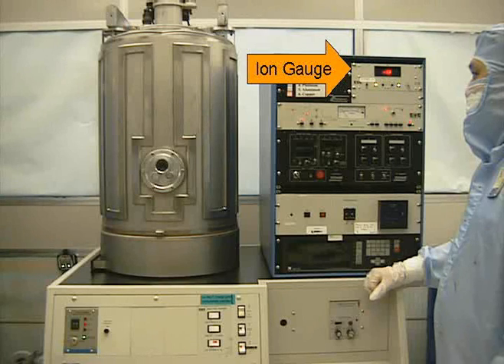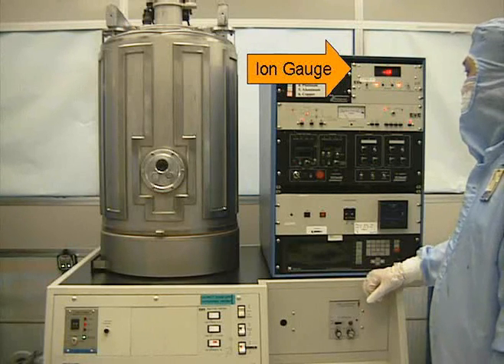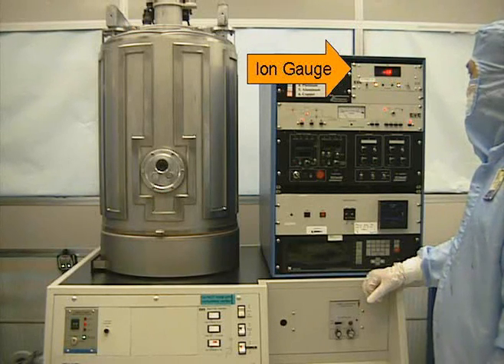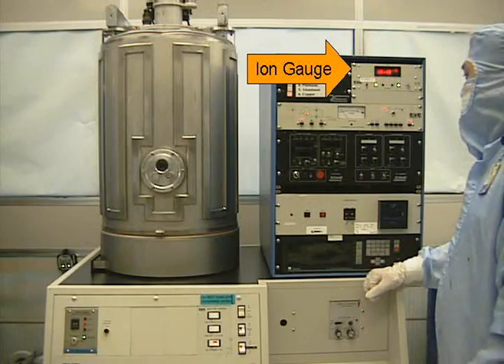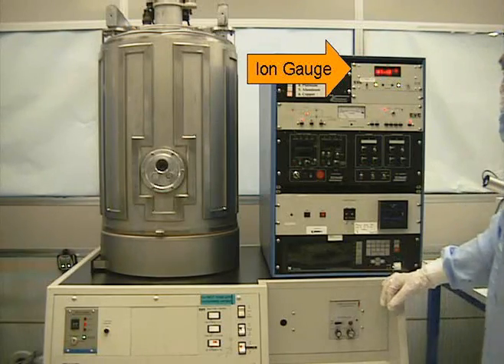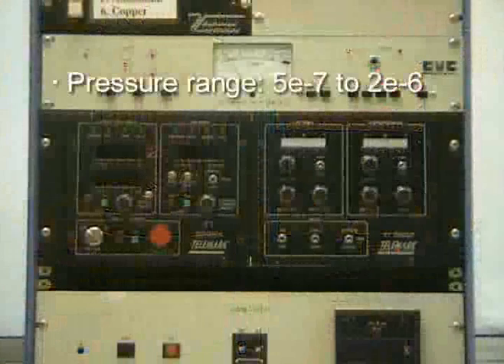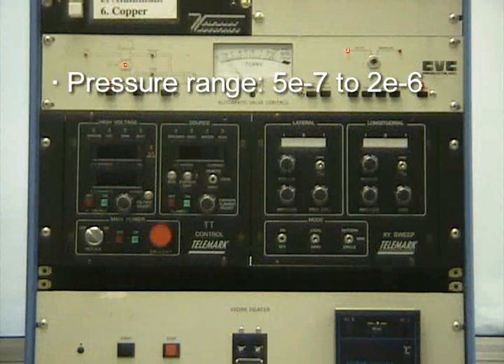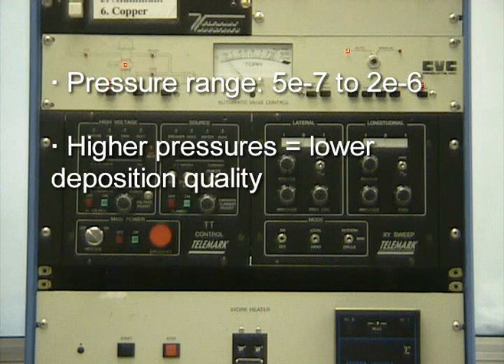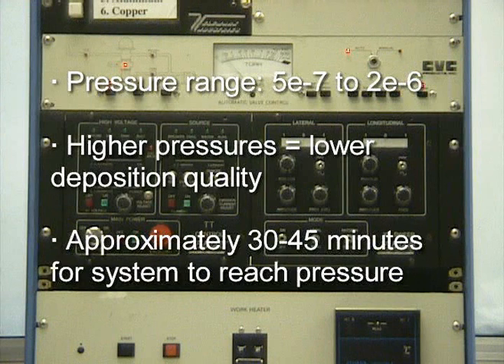Soon after, the ion gauge controller will come on. This is indicated by the lights on the ion gauge controller changing from red to green and the counter displaying the decreasing pressure of the chamber. We will wait for the pressure to come down to about 5 times 10 to the minus 7 to 2 times 10 to the minus 6 range. However, if you are not concerned with the deposition quality, you can start at higher pressures. If you want a low pressure, it may take 30 to 45 minutes for the system to reach the pressure you want.